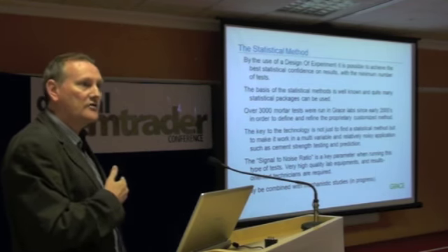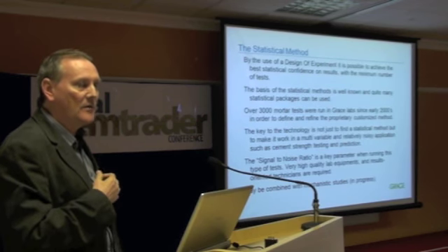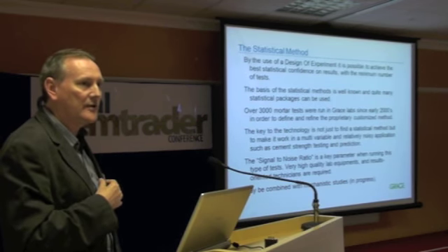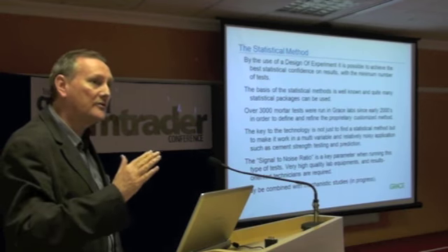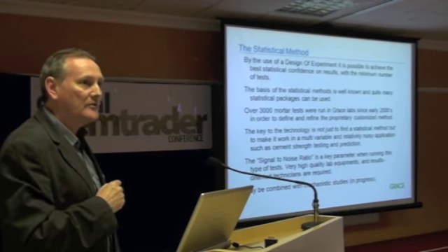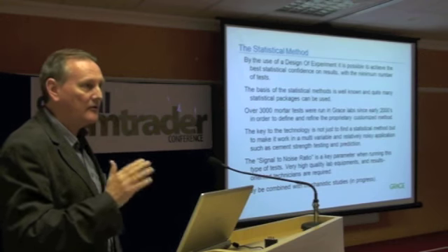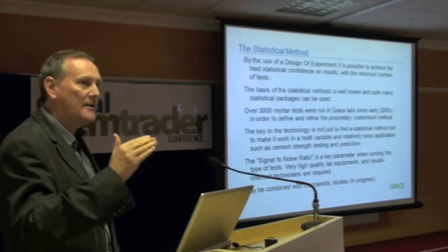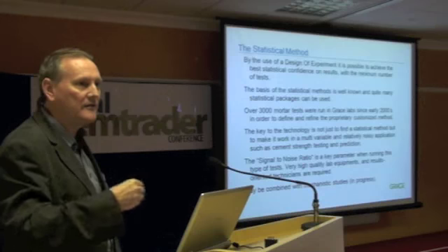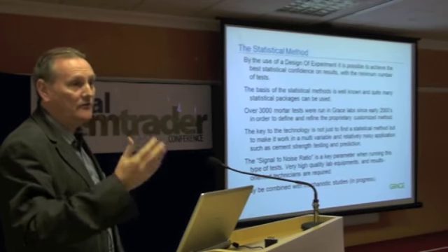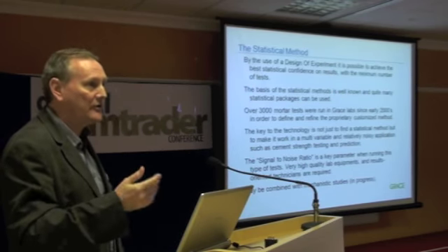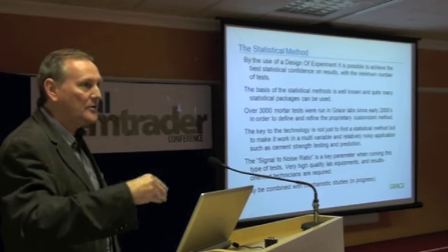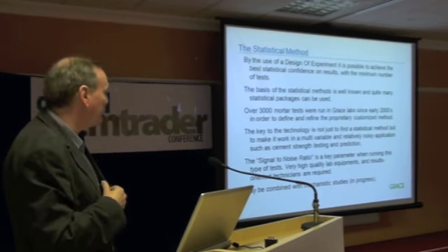So one of the keys to customization is to really minimize your coefficient of variation in your testing environment, which we'll call the noise, because you're looking for a signal. So this signal to noise ratio is incredibly important. If you have a high noise, high standard deviation, and you want to look for a small signal, you've got to do thousands of tests to be statistically confident it's real. So the lower you get the noise, the more you can reduce the number of tests.